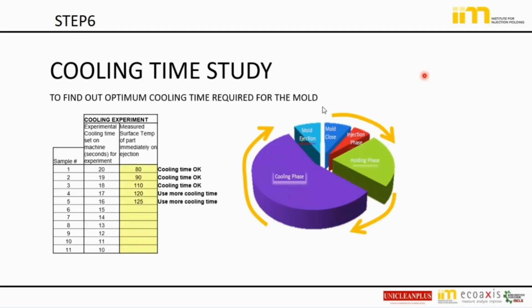So here what we are doing, we are always starting with optimization. We wish to reduce the cooling time. So we start with higher cooling, suppose 20 seconds. Suppose this raw material is polycarbonate, whose HDT, heat deflection temperature, is 120 degrees. It means I can eject the part out below 120. There will not be any deflection. That is good enough. Maybe 110 and 100.